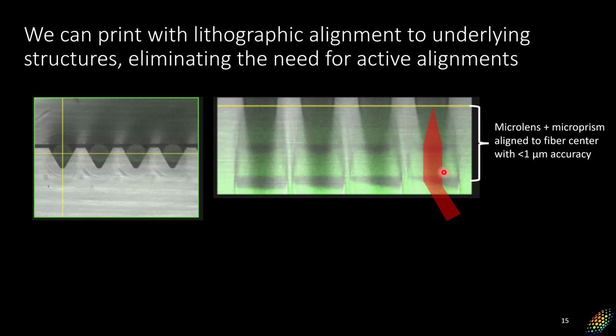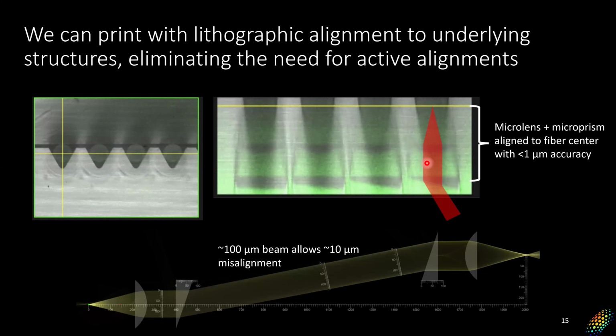And so this lens and prism pair means that you can now take this light, collimate it to whatever size you want, and then bend it and send it off in whatever direction you want. So you can build collimated beam connectors where you have a sender on this side and a receiver on this side, where instead of needing to line up a 10 micron mode field on a fiber or a 2 micron mode field on a PIC, you just need to align this hundreds of micron expanded beam between the two, where each one separately has this lens prism pair printed on it.